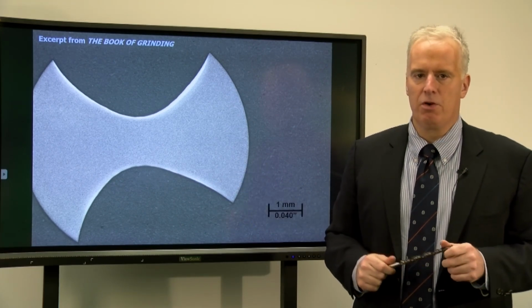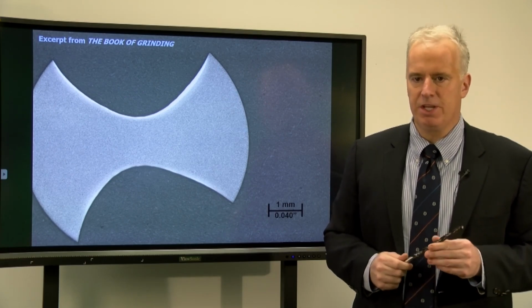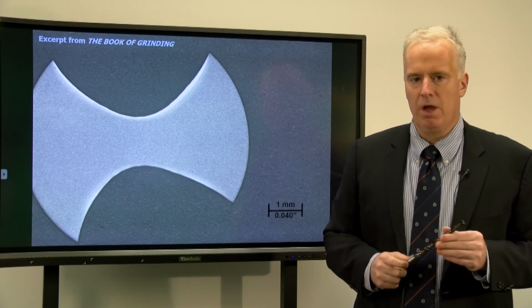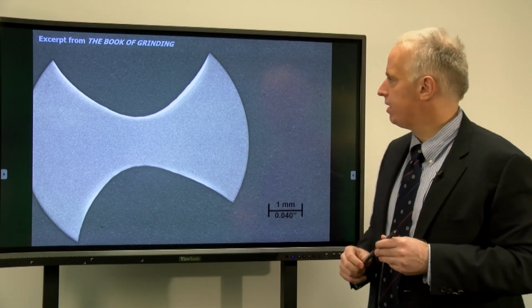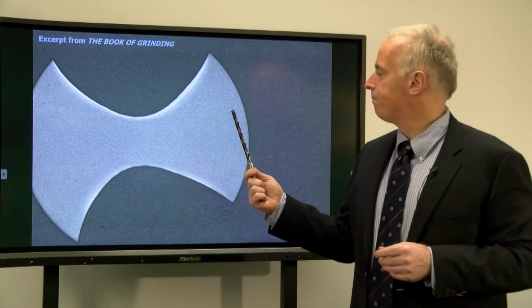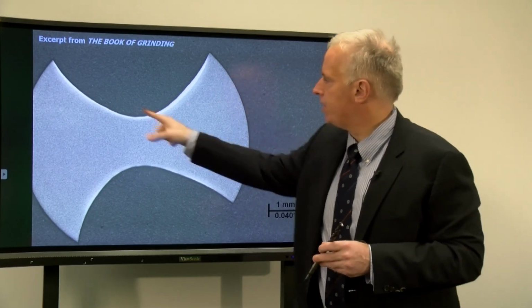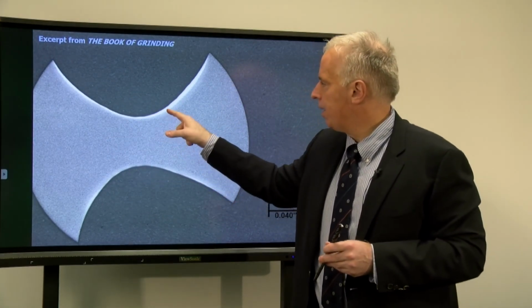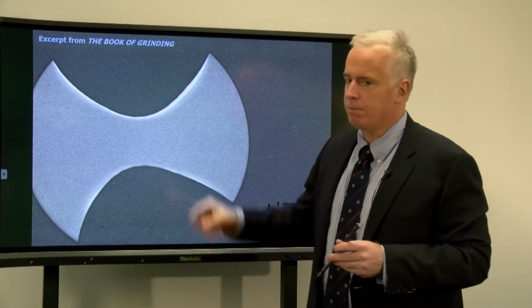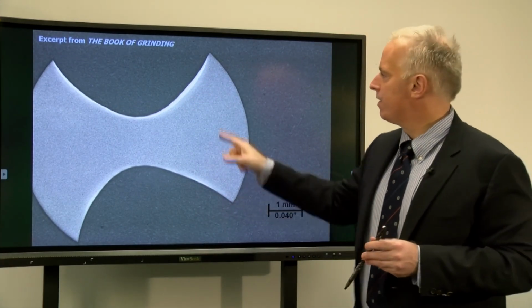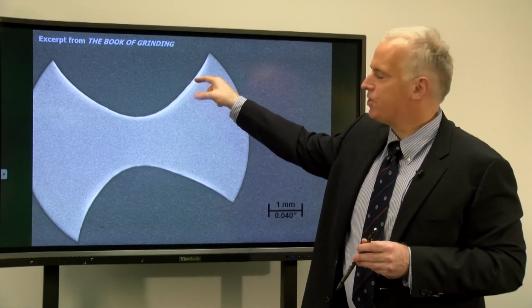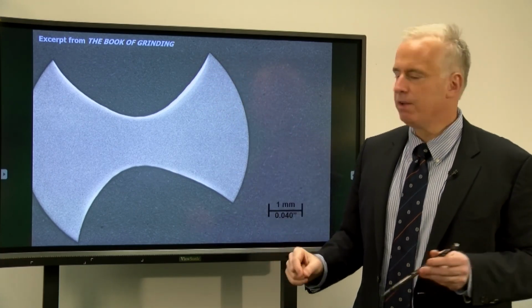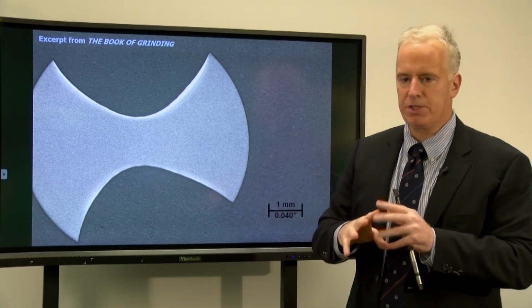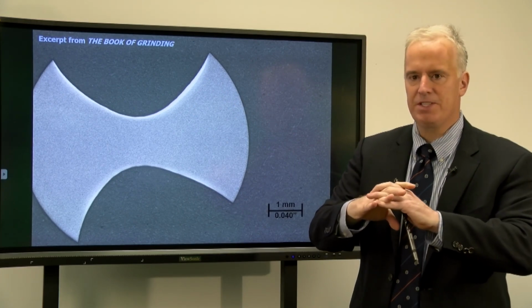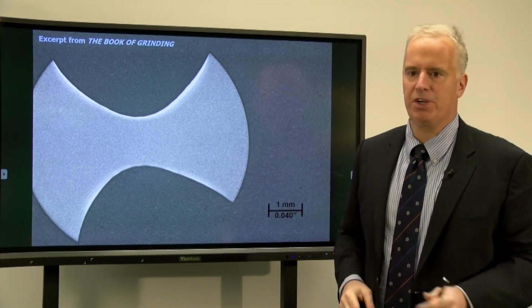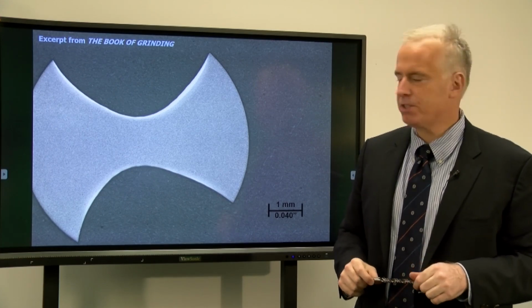And then the worst type of thermal damage in steels is what's called rehardening burn, where you actually get a phase change in the material. So this is some kind of drill bit or end mill, and we have the flute grinding operation here. We've got two flutes, and what we have is the white layer, some people call it, and the white layer is where the steel has changed phase. It hasn't melted, but all those little molecules in that crystal structure change phase and they realign to a different crystal structure. We have body-centered cubic, face-centered cubic, stuff like that.